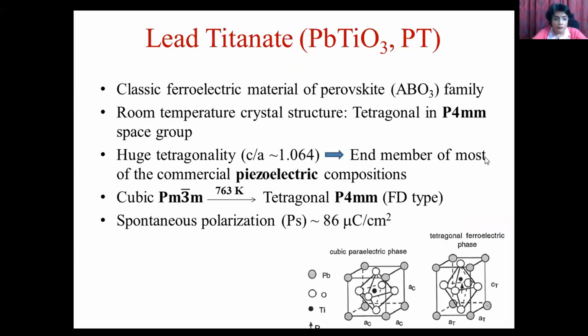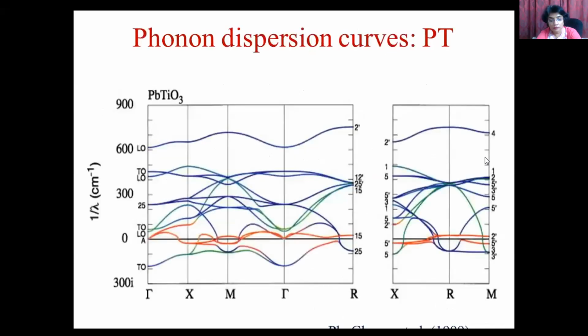Now talking about lead titanate. Lead titanate is a very popular classic ferroelectric material. At room temperature, it has a tetragonal P4mm space group crystal structure, and because of this huge tetragonality, it is very popular because it is the end member of one of the most popular commercial piezoelectric compositions. It has very high spontaneous polarization, which has been calculated at 86 microcoulomb per centimeter square.